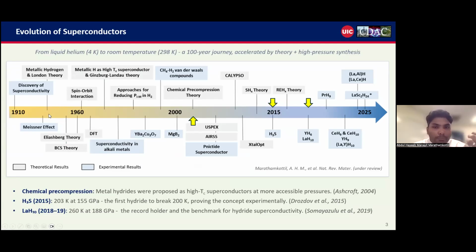The foundation goes back to the 1930s, when it was first proposed that under extreme pressure, hydrogen would form a metallic lattice and behave like an alkali metal: metallic hydrogen. Ashcroft connected this to superconductivity in around 1968, applying BCS theory. He argued that metallic hydrogen, because of its uniquely light mass and strong electron-phonon coupling, should be an exceptionally high temperature superconductor, potentially at or above room temperature.